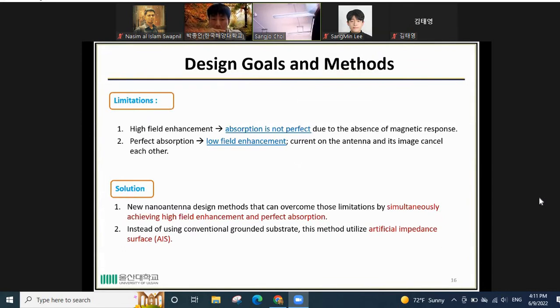However, the design that I mentioned has a limitation. In such a high field enhancement structure, the absorption rate is not perfect because of the absence of the magnetic response. And also the structure with perfect absorption has low field enhancement because the current on the antenna and its image cancel each other. So as a solution to this problem, we try to design a nano antenna that can overcome those limitations by simultaneously achieving high field enhancement and perfect absorption. Also, this design method uses an artificial impedance surface instead of a conventional grounded surface.